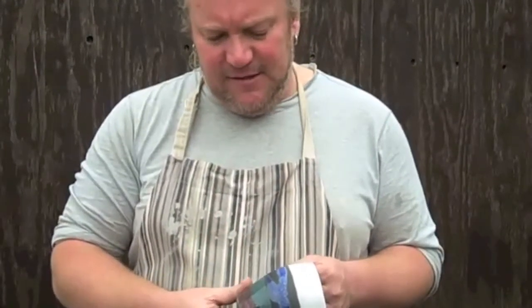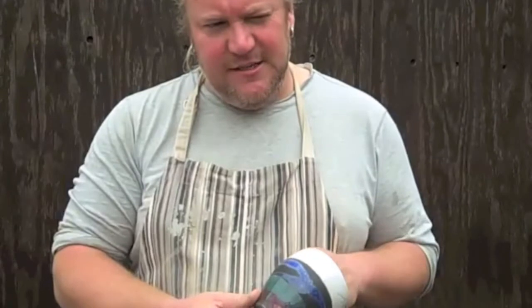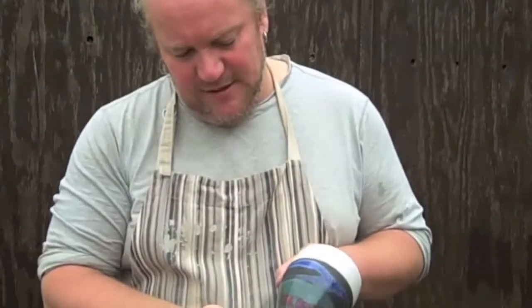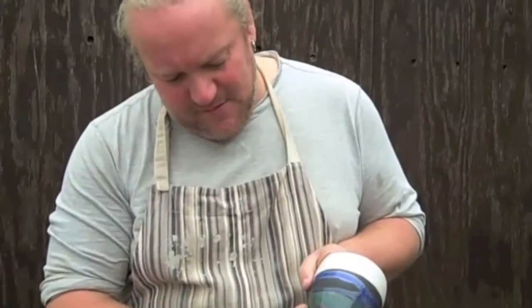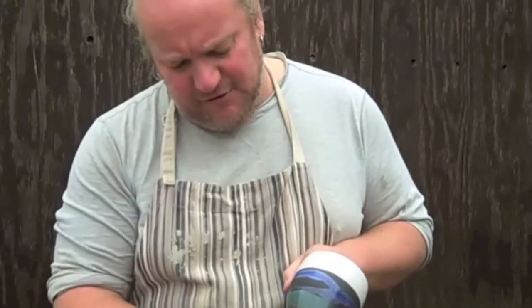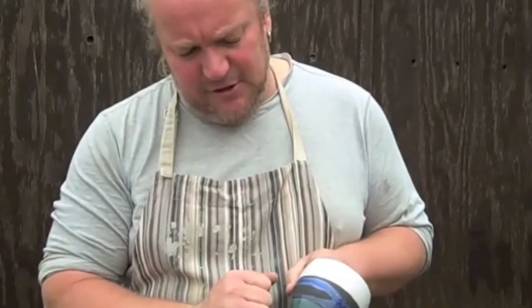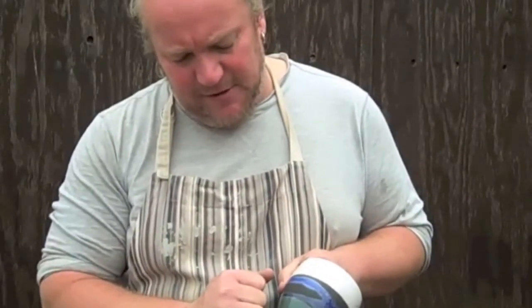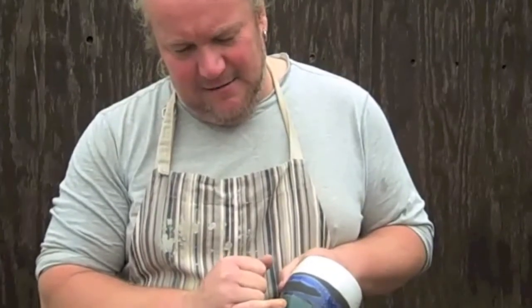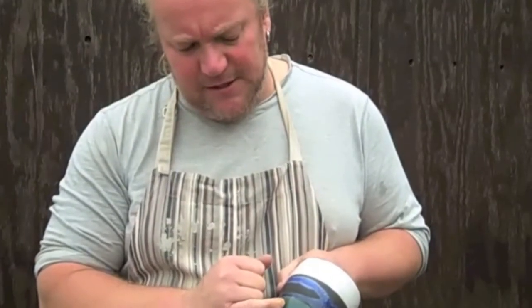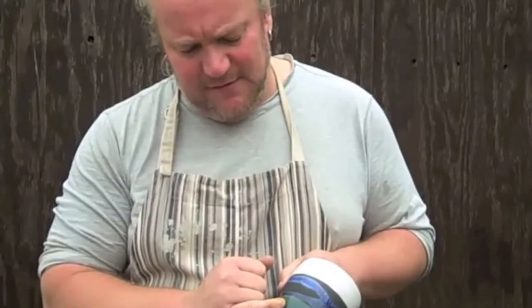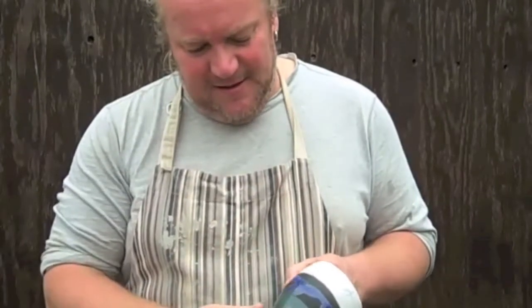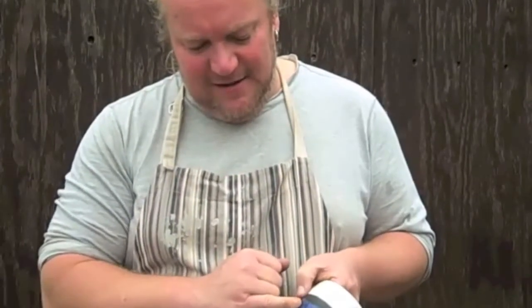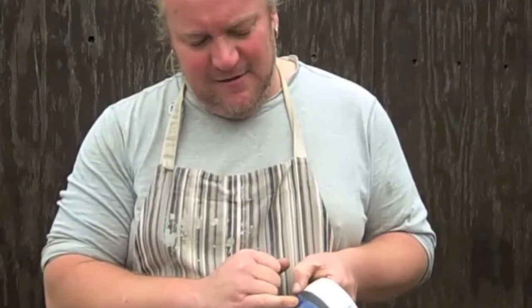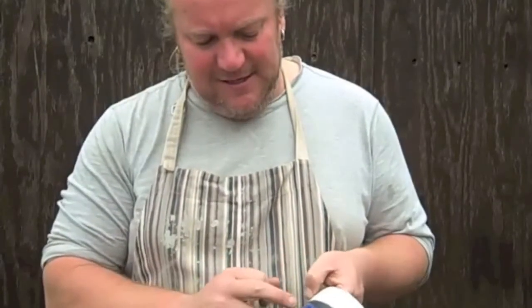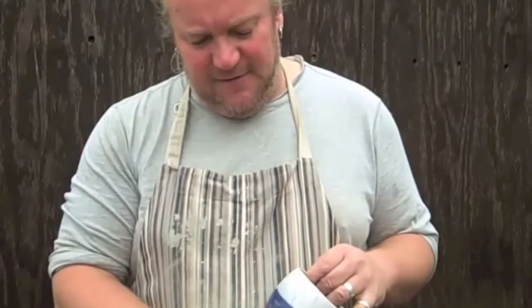When it's gone into the kiln, it's come out of the kiln at 1000 degrees, it's put into the sawdust, and where that sawdust has almost made a line where it's reduced heavily in the bottom of the pot, which is why you've got these coppery colours coming through. This pale blue turquoise colour is more of an oxidised finish. The glaze is crazed and the burning of the carbon in the sawdust has highlighted the craze. That's a finished pot.